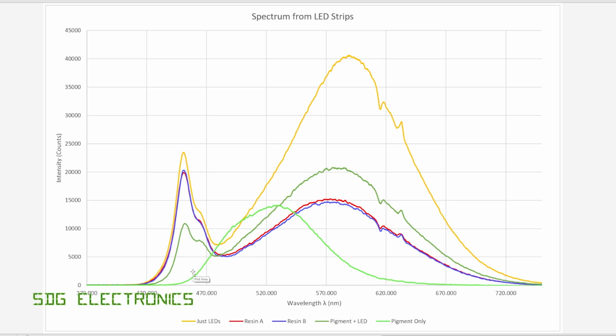Then what we have in green is the output from the LEDs that were encased in the resin combined with the glow-in-the-dark pigment. Now this one's quite interesting because the resin itself was poured a little bit thinner, which explains why we see a little bit more light in this region here. But more interestingly, what we're seeing is quite a significant decrease in the amount of light in the 450 nanometer region. And that's because the glow-in-the-dark pigment is actually absorbing the light in that region and then refluorescing in the sort of 500 to 520 nanometer region.